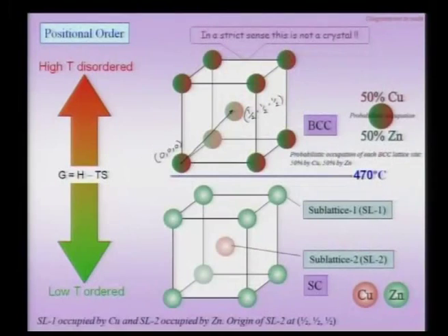We have already noted that in the very strictest sense this structure cannot even be called a crystal. This is a crystal only in the probabilistic sense, and given that important point, this is actually a BCC crystal with the fundamental lattice translation vector, or the shortest lattice translation vector being half half half, whose length is √3/2 a. See, all these aspects we have already seen.